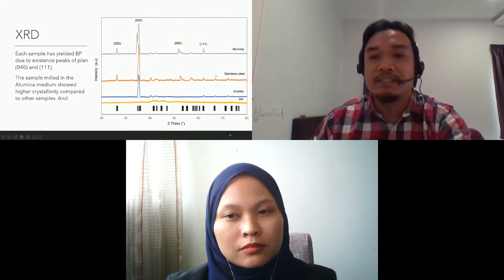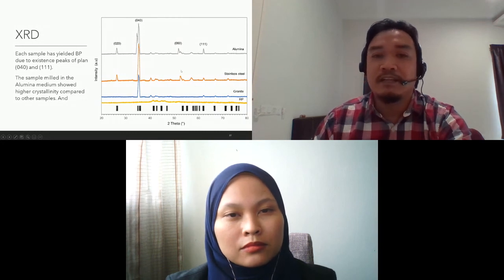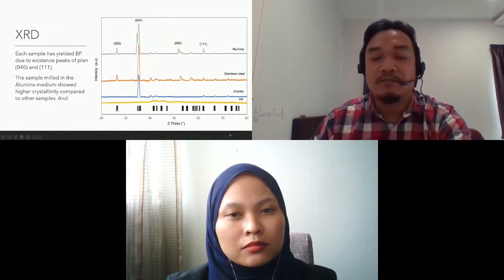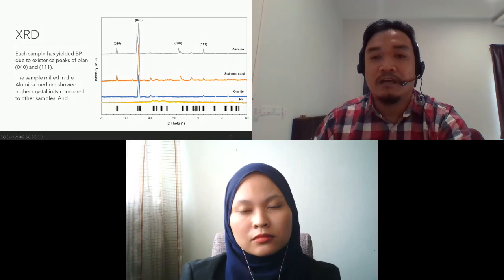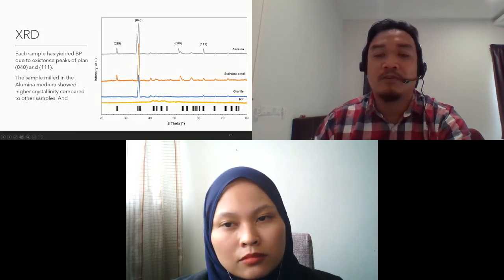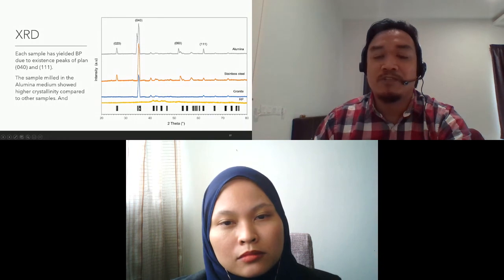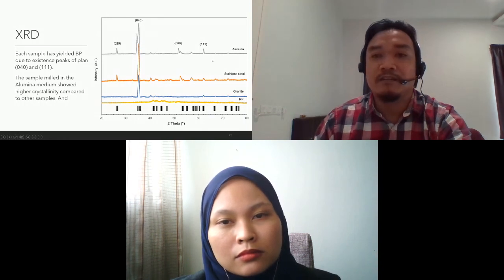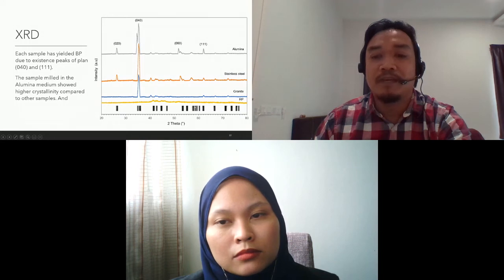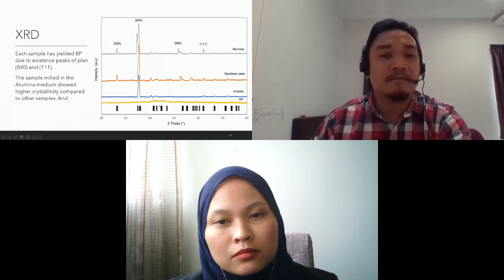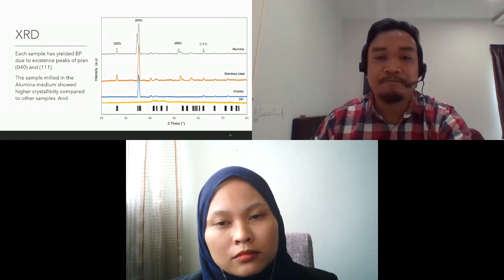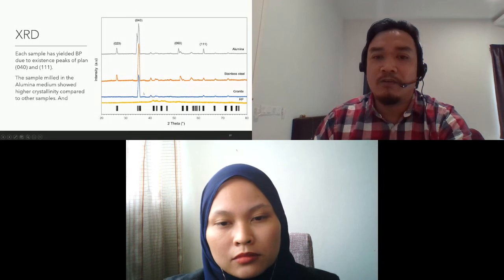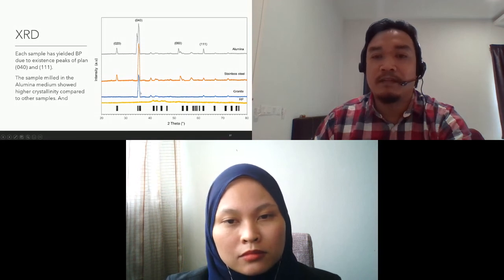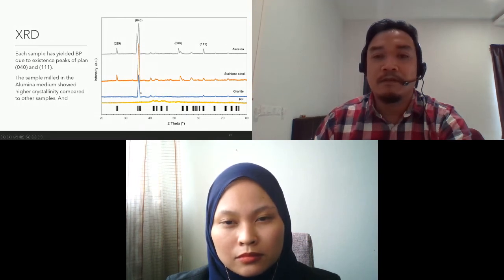And for the XRD, we can see here the alumina and stainless steel have the X-ray diffraction for the BP, as can be seen in this graph. This is the standard black phosphorus line. We know that by using alumina and stainless steel, all the peaks signify the BP existence. However, the granite also has significant peaks here, but they are missing some of the BP peaks.